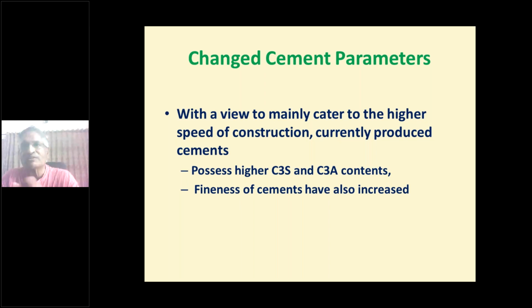This is what we want because we want to de-shutter fast and finish the work as fast as possible. So speed has become an important parameter in construction, and the cement manufacturers are helping it by producing cements which can gain strength faster. The process is they increase the C3S and C3A contents, and the fineness of cement has also increased.